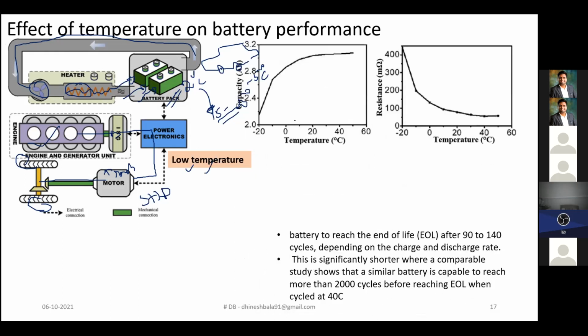When you make a plot of temperature versus capacity, we are aware that the optimal temperature limit lies between 15 to 35. 15 to 35 gives you the maximum capacity of your lithium ion battery. But as the temperature falls below, the capacity slowly starts to fade out to a greater percentage. The internal resistance is very nominal between 15 and 35, much lower in terms of milliohms. But at well below sub-zero, it would be 5 times higher: assuming 100 milliohms, it would reach around 500 milliohms when you try to charge or discharge your battery at a sub-zero condition of minus 22.